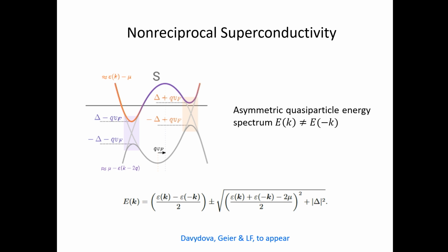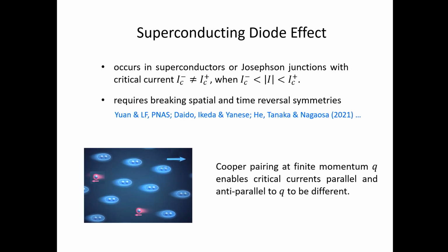so one of the challenges in understanding the superconducting diode effect is that it requires measuring the asymmetry of the critical current. One has to apply a large current to really destroy the superconducting state, to drive the system from superconductor into a normal metal. And in the case of a large applied current, there could be problems with Joule heating, could be problems with vortex dynamics. So that makes it challenging to disentangle the intrinsic superconducting diode effect from more mundane mechanisms.